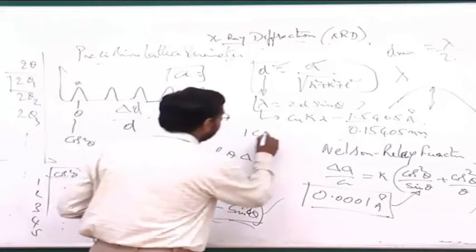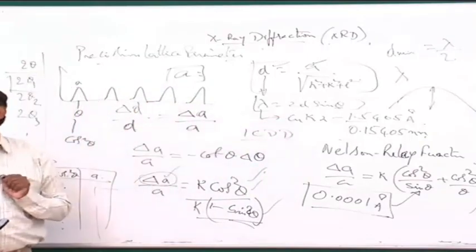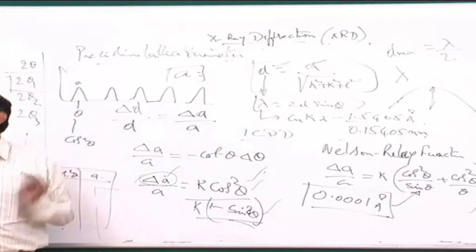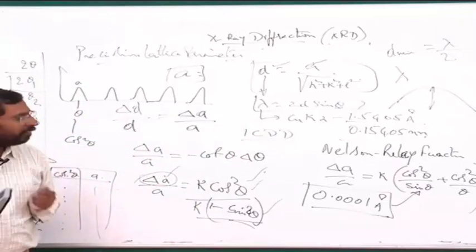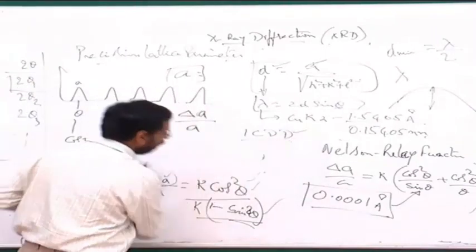So what people regularly do, for complicated structures, is simply depend on ICDD. If your XRD pattern is perfectly matching with that particular diffraction pattern, whatever lattice parameter is shown for that particular structure in that data handbook is what is taken as the lattice parameter. This is an easy way to do it, but of course that has to be confirmed. The reason why you need to confirm this is this. Many times your phase may not be exactly matching with this.